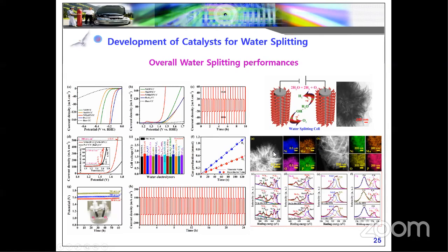This is confirmed by the SEM EDS analysis. You can see the phosphorus, which is easily degraded or converted into oxides. In our case, the phosphorus is fully retained in both the HER side electrode and the OER side electrode. And this is the initial one for nickel, manganese, oxygen and phosphorus. After HER and after OER, the nickel 2p 1/2 peak shifted slightly towards the higher region, in the case of manganese and nickel. And in the case of non-metallic elements like phosphorus and oxygen, it shifts towards the lower region.